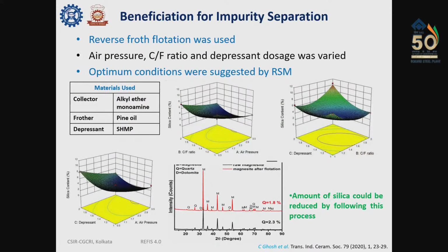In another approach, we use the reverse flotation process to separate the impurities. Mainly, our aim was silica, and we used alkyl ether monoamine, and pine oil as a frother, with SHMP as a depressant. We adjusted several parameters, and in this reverse flotation process it is possible to remove the silica. So it's a preliminary work. We need a lot more work to do with this.